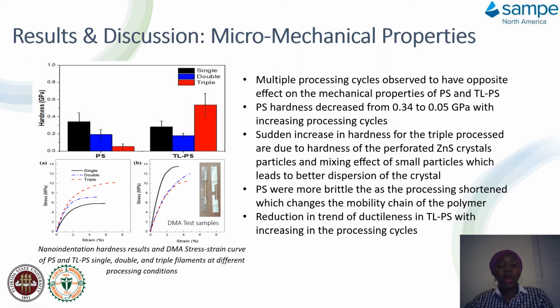extrusion for polystyrene. However, for the composite, it shows that the 3rd one is much more ductile than the 1st extrusion, and this is due to the increase in the processing cycle of the composite. And for the polystyrene, the processing shortens the mobility of the chain in the polymer, which makes it more brittle. And because there is TL inclusion in the composite, it reduces the trend in the ductility compared to polystyrene.